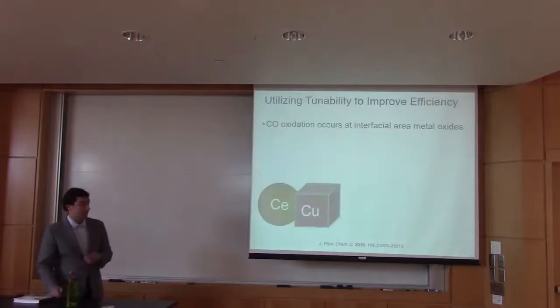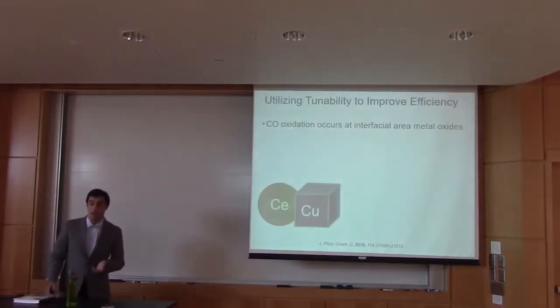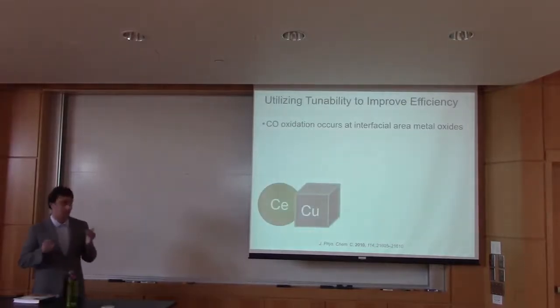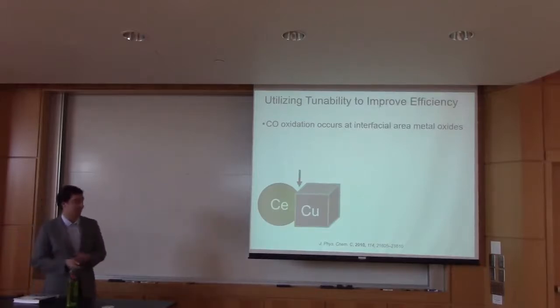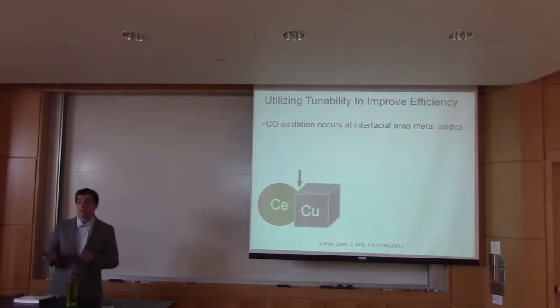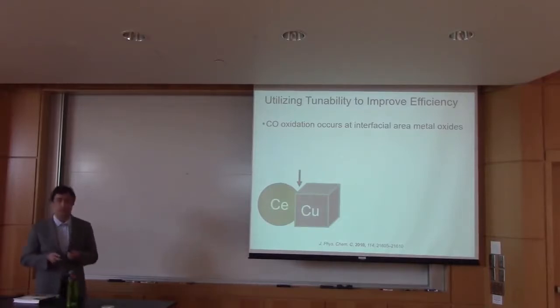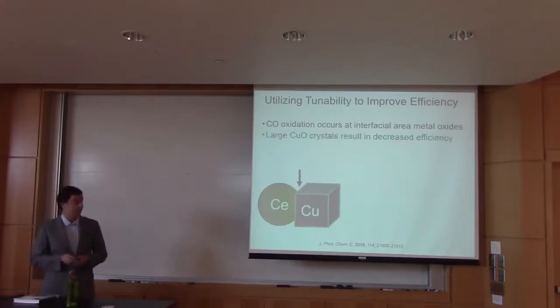And we want to do this because previous work has shown, first and foremost, the chemistry that we're hoping for is going to occur at the interfaces of these ceria and copper oxide domains, which is right here or right here. Again, very simple representation. But previous work has shown that these catalysts perform less efficiently with large copper oxide domains.